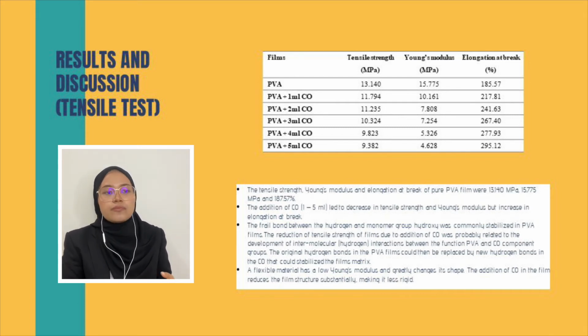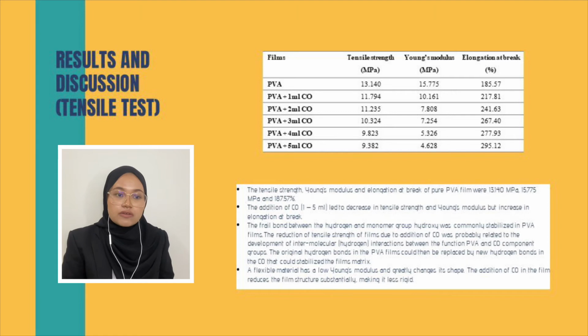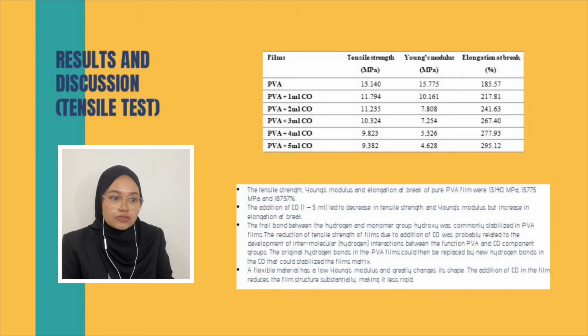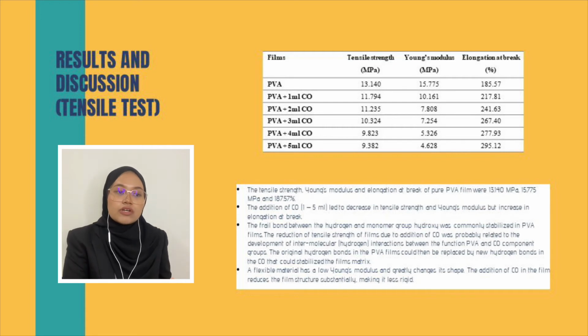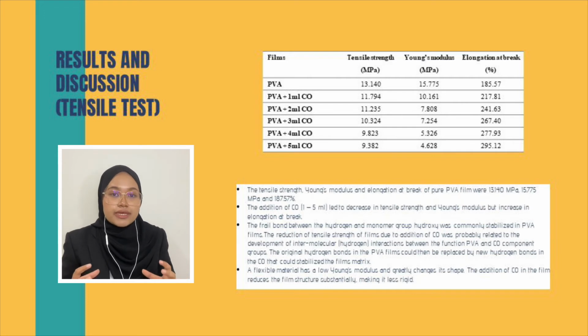This is because the bond between the hydrogen and the monomer hydroxy group was commonly stabilized in PVA films. The reduction of tensile strength of the film due to the addition of CO was probably related to the development of intermolecular hydrogen interaction between the functional groups of PVA and CO components. The original hydrogen bonds in PVA films could then be replaced by new hydrogen bonds with the CO, and that could stabilize the film matrix. The addition of CO in the film reduced the film structure, making it less rigid.